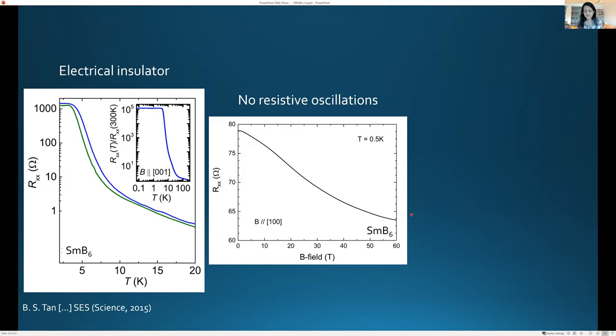We search for, I don't know, several months. We don't see anything, and we decide we can't make any conclusions from this one way or the other about whether there is a conducting surface or not, because if you don't see oscillations, it doesn't mean there's no Fermi surface. It just means maybe the amplitude is too small for you to see. So we're sort of winding down at that point, deciding we can't make a conclusion.